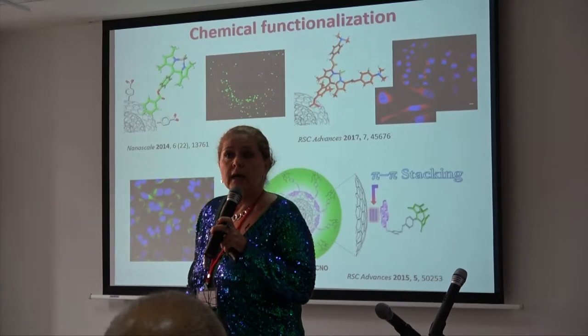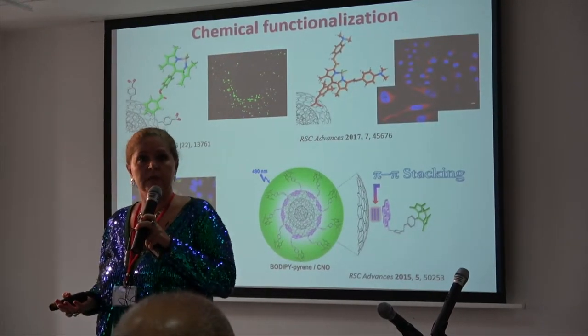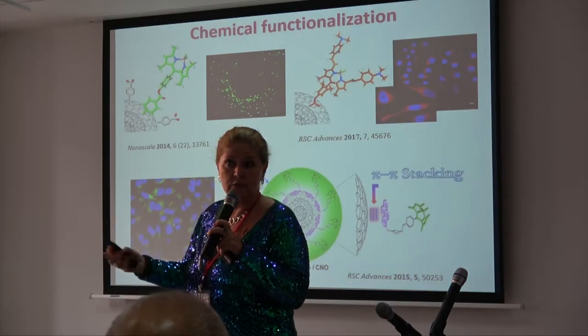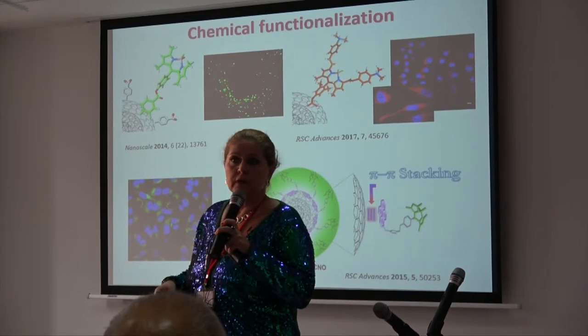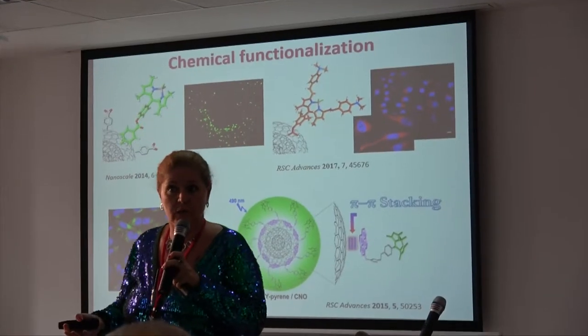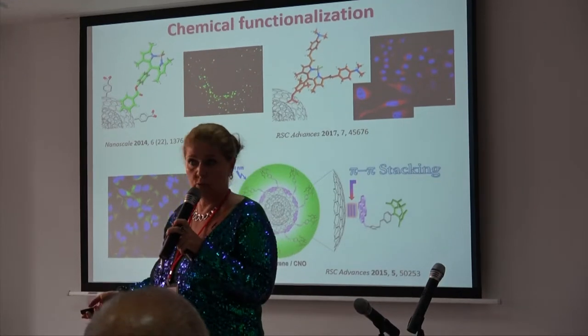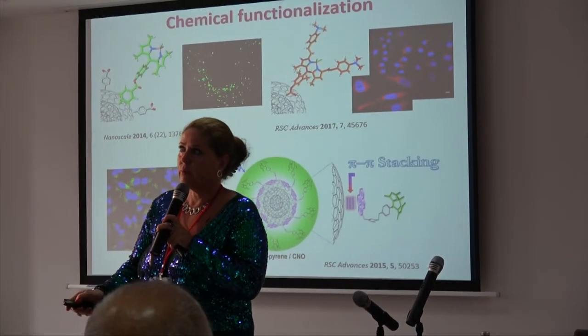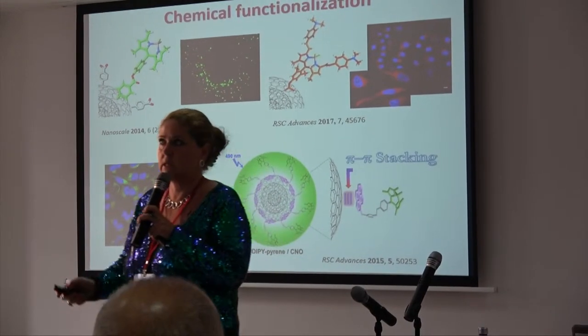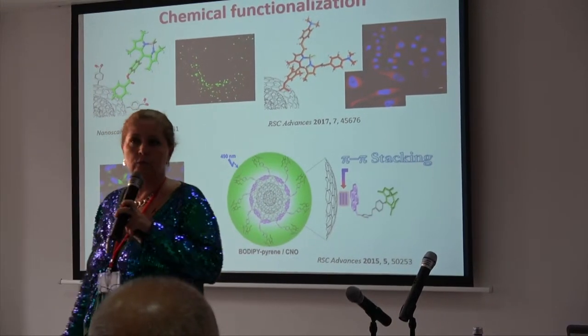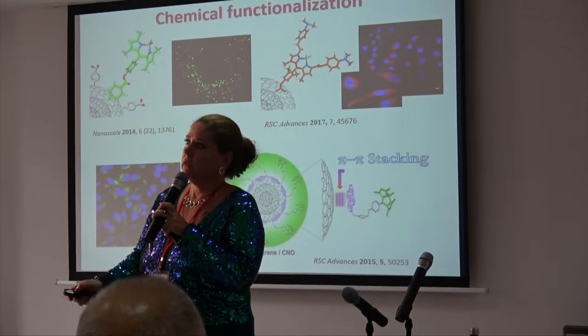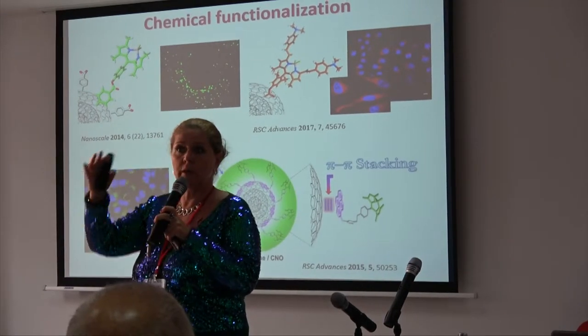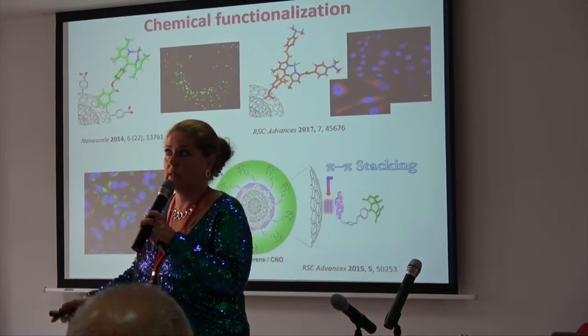What we do in the lab is chemically functionalize the surface in order to render them fluorescent, for instance. We have developed different ways to do chemical surface functionalization, both covalent and non-covalent. In the covalent approach, we covalently grafted green and red fluorophores, and in the non-covalent we can avail of the graphitic structures and using pi-pi stacking we can also bring different molecules.